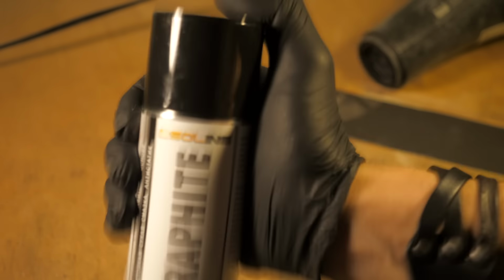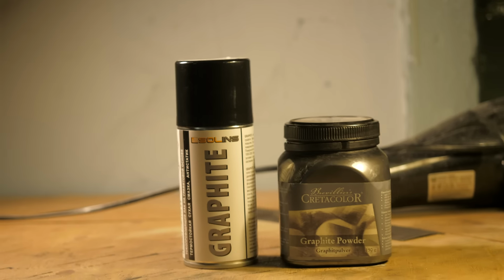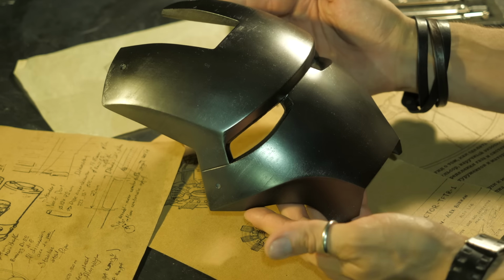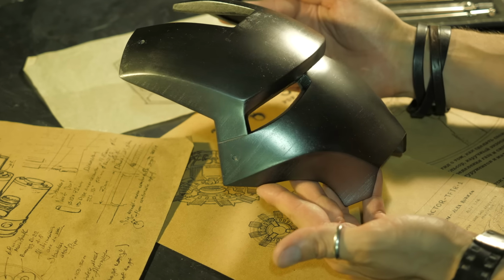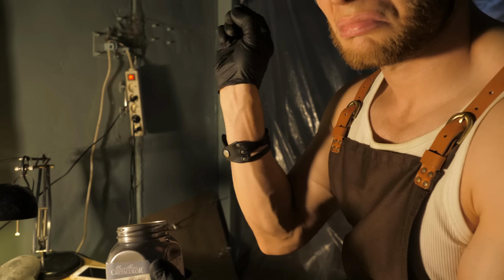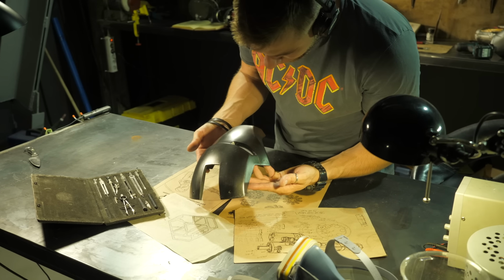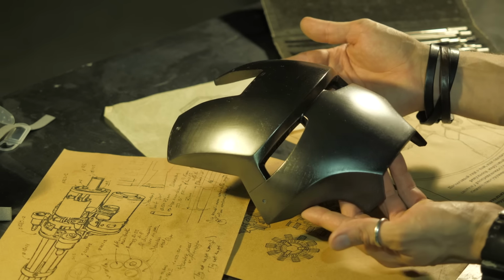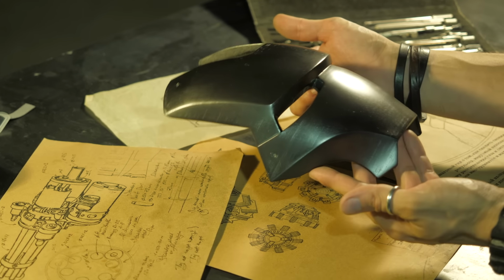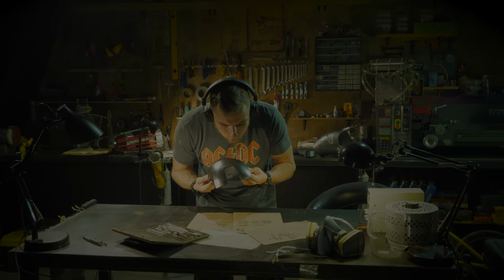To do this, first cover the mask with a couple of layers of graphite varnish. Without waiting for the varnish to dry completely, add our secret ingredient, graphite powder again. The graphite powder, combined with graphite varnish, creates a smooth and dense conductive coating.